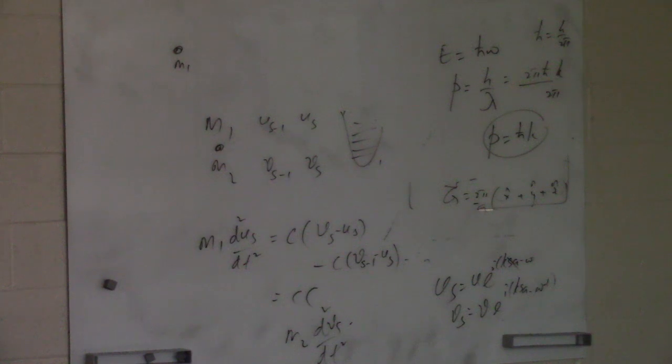Actually, experimental people have measured this for argon crystal at low temperature. So argon at low temperature, they form some FCC crystal. If you look at this one, you can see this lattice constant. They measure the lattice constant. Lattice constant is basically expansion, right? If it changes with temperature, that tells you this. So if you measure that one, actually you find this part is pretty linear temperature dependent. This is real experimental data. And also density. Because if the expansion changes, it means your density is also changing, right?